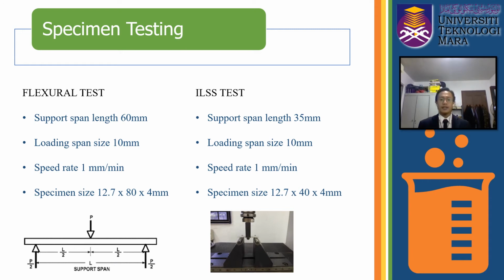For the ILSS test, the specimen size is slightly different from the flexural test, which is 12.7 mm times 40 mm times 4 mm. The support span length of 35 mm is quite shorter than the flexural test, and the loading span is the same as the flexural test, which is 10 mm. The speed is also the same as the flexural test, which is 1 mm per minute.